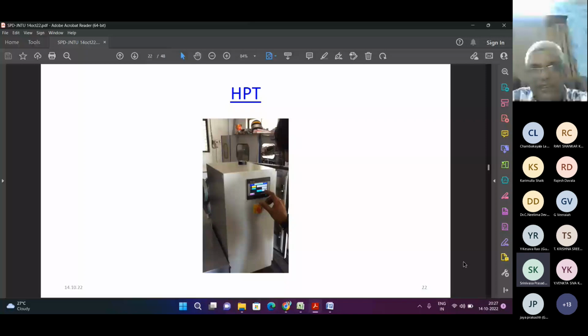It is kept in Basaveswara Engineering College. Recently I had been to that place. Why? Because whatever we have done in London, we compared with some of the same material we used here, and the results are almost the same. So the machine we have developed is extremely useful, and you can apply pressures up to 5 GPa. The only thing is, the size of the sample is very, very small. Next slide.